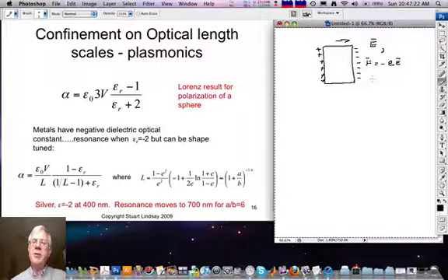This then gives a force on the electrons proportional to this electric field, pulling them back into the material. And by using Newton's second law for the displacement of charge, which I will call d here, one then arrives at an equation whose solution is simple harmonic motion at a frequency omega p, of course an angular frequency 2 pi f, which is given by n, the number of electrons per unit volume, times their charge squared over their mass times the dielectric constant of free space.